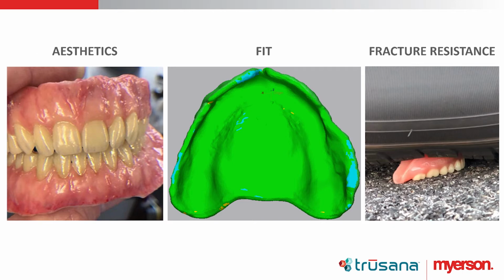I would say we should hope to hit 200 microns in overall dimensional accuracy. But really, we're shooting to be as accurate as we can, at 100 micron overall dimensional accuracy. Most of the materials, especially Trusana, we see print very accurately. We're seeing 95% plus at 100 micron accuracy. So that's a very good spec to meet. We know that this material, as we print it, is consistent, accurate, and going to fit in the mouth.